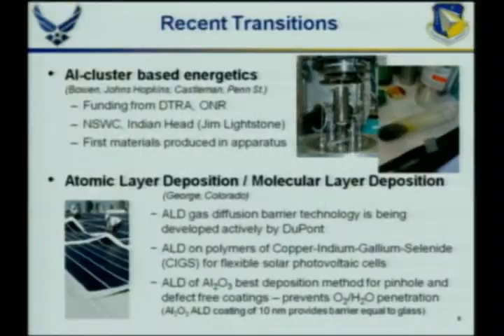Some recent transitions from the program itself. I mentioned some novel types of energetic materials we looked at in our program, particularly with Kit Bowen at Johns Hopkins and Will Castleman at Penn State, in developing these energetic aluminum clusters that are both energetic and stable to oxidation. We funded some of this initial work. It's been picked up now by folks at DTRA and ONR to try to turn this into a larger-scale process and make more macroscopic materials. Jim Lightstone at Indian Head is developing some of this in the Navy 6.2 programs.